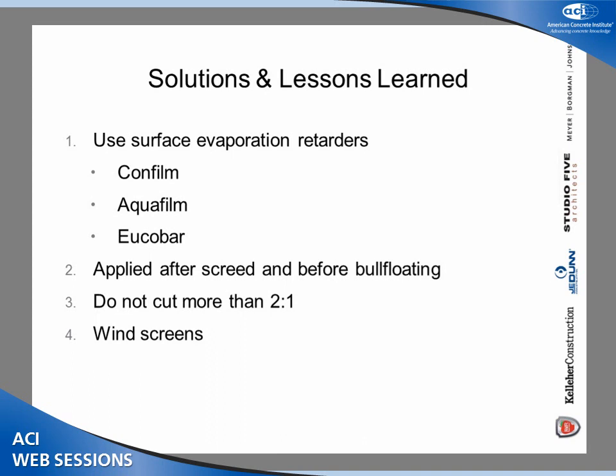Again, now this is a little controversial, but it's worked in the field. Applied after screed and before bull floating. People say you shouldn't be working a surface retarder into the surface of the concrete. This is true, but I have not seen any significant deleterious effects from doing so, because then after the bull floating, again, depending on the conditions, let's say it's a windy day, a dry day, you have to keep that surface alive, especially in the wide module pan and joist, so you get that bottom to top set. And so we have them reapply the surface evaporation retarder to keep that surface alive until they can get on it and finish it. The other mistake that's made is the contractors will sometimes take that Confilm or Aquafilm and they'll cut it 5 or 6 times to 1, and you really eliminate its effectiveness when you do that.